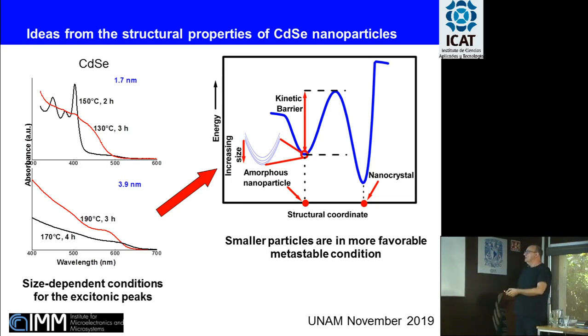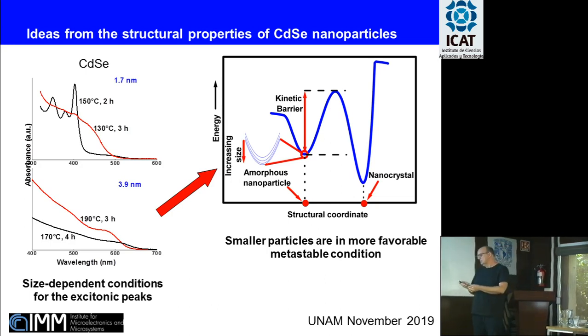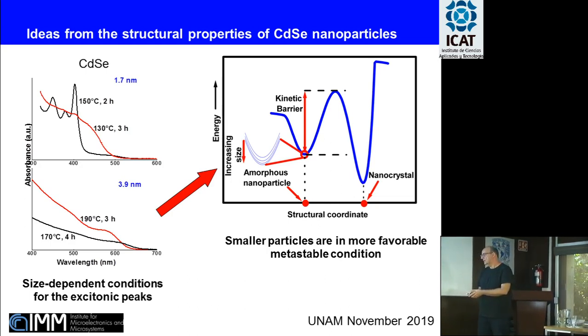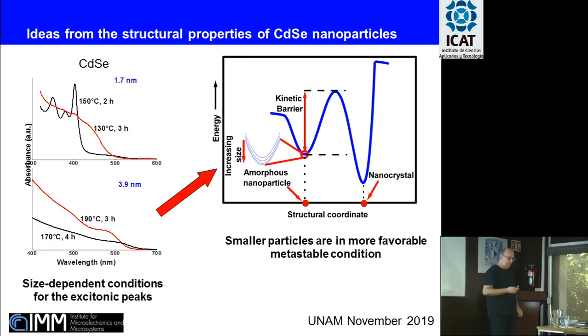This can be seen in this schematic figure where our amorphous particles have a different starting energy, so that the smaller nanoparticles have some less stable configuration toward higher energies, and we need less energy to overcome this kinetic barrier going to the nanocrystal formation. But what was important was this conclusion. Smaller particles are in more favorable metastable condition. Cadmium selenide nanoparticles. What is the connection with our work about oxide?